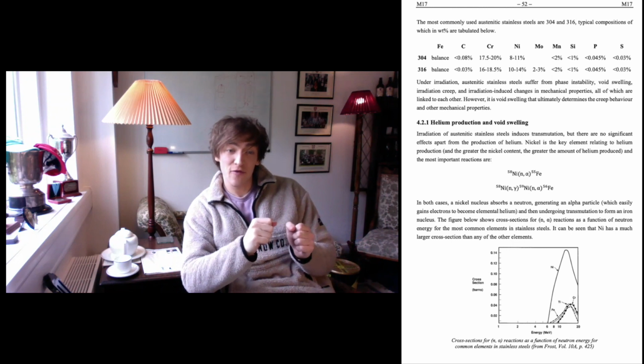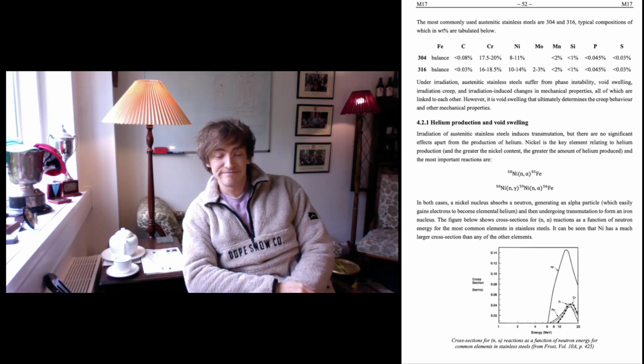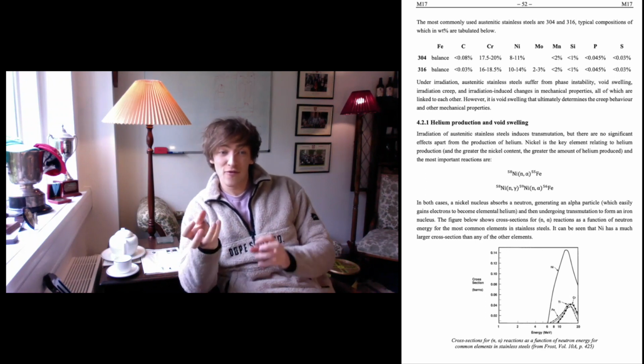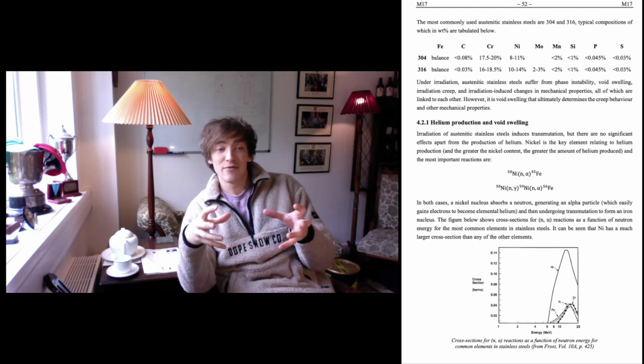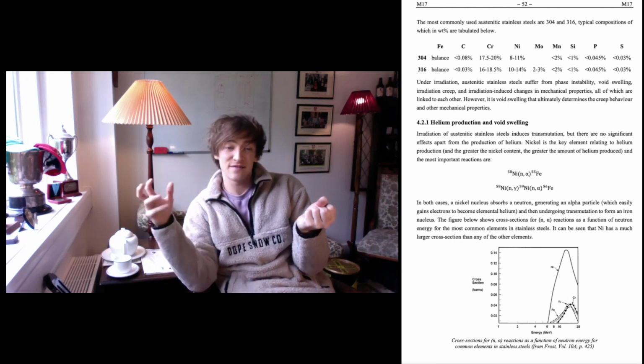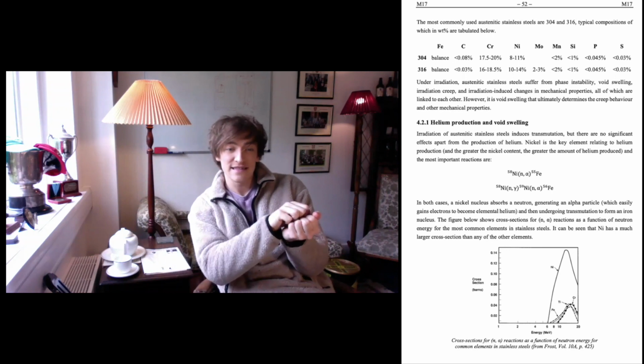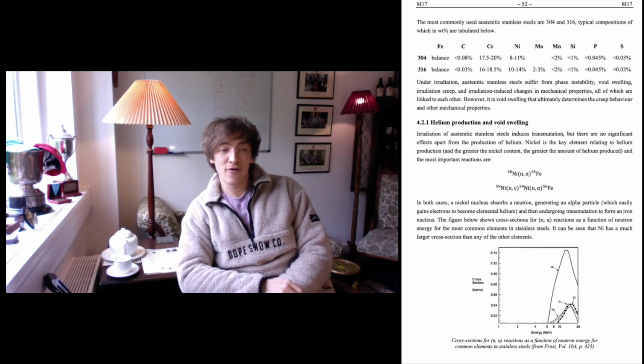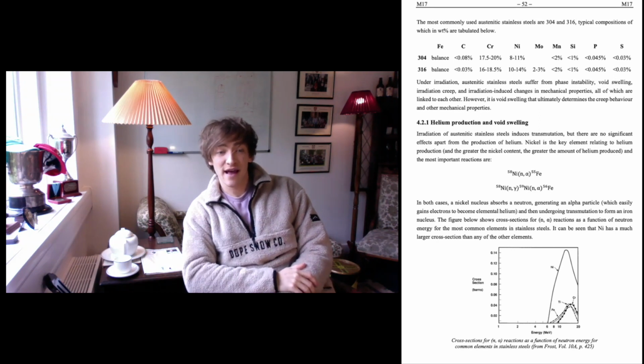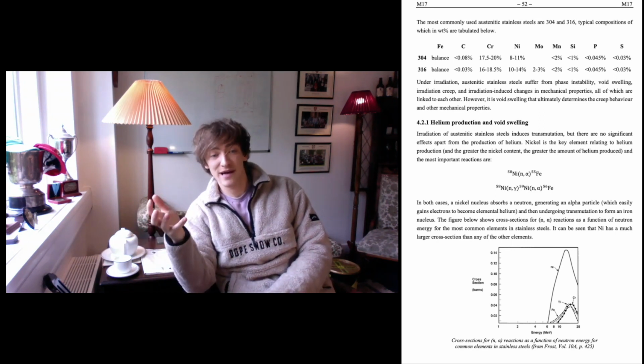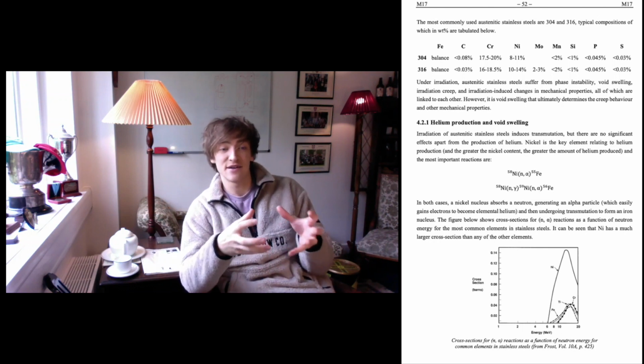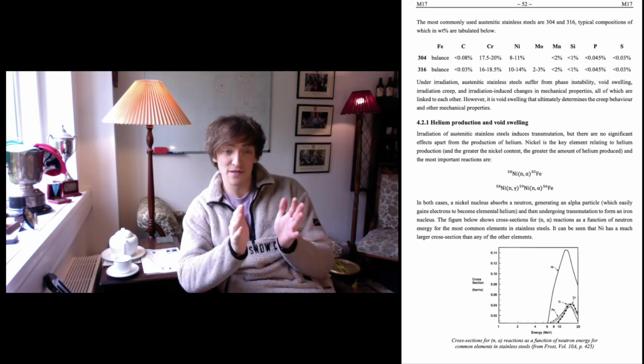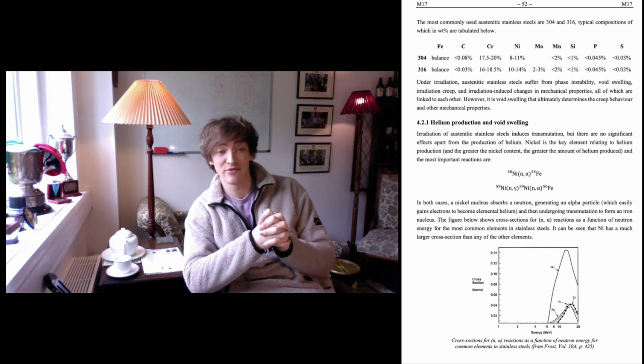And that's because of something I mentioned before, three words: gas-assisted nucleation. Meaning helium bubbles that form from all this helium you're making from transmutation will act as sinks. They're tiny, but they act as sinks for vacancies that travel randomly and sit in these sites, and therefore they become nucleation sites for voids, and that in turn accelerates swelling. So you've got gas-assisted nucleation of voids. So the incubation period after which you would normally expect swelling to occur is shortened significantly when you've got helium being produced.